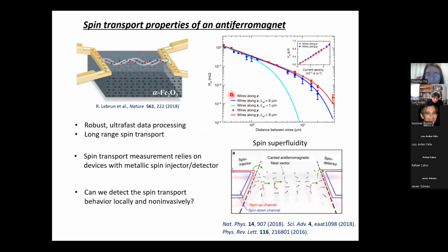So for the state-of-the-art measurement of the spin transport properties, typically it takes advantage of this non-local measurement geometry. So we have a material and we pattern two metallic strips on top of the material. We use one strip to inject the spin using the spin Hall effect or the thermal gradient. Then the spin will diffuse inside of the material, and we can detect the spin accumulation using the inverse process of the injection, using inverse spin Hall method, for instance. So this has been applied to a broad range of material systems, for instance, alpha iron oxide, as well as two-dimensional material systems that can potentially host spin superfluidity.